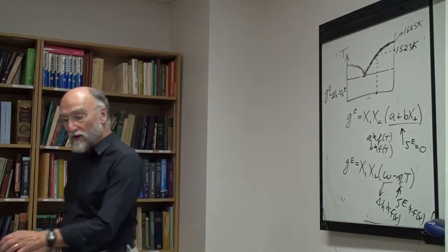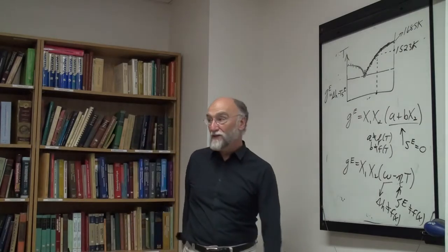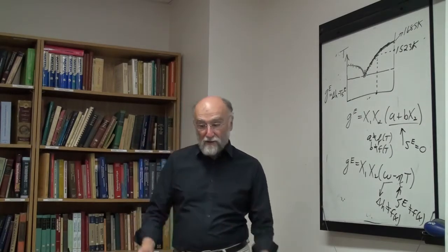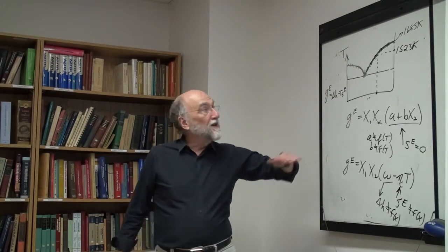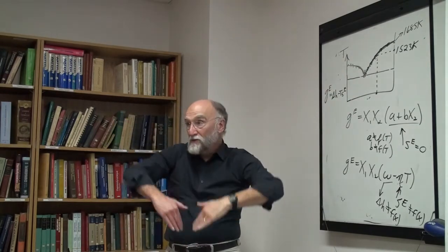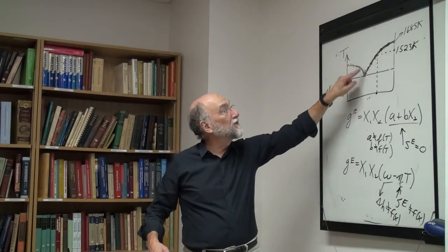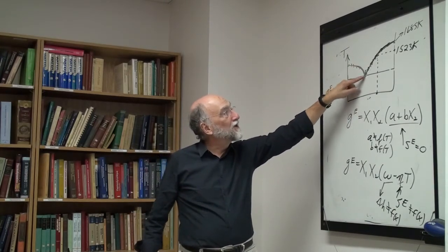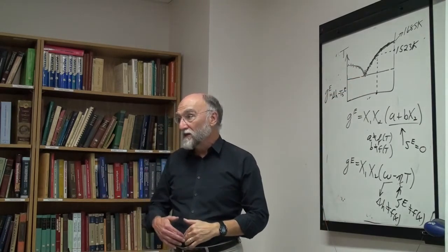And why is this important? If all you're trying to do is fit the binary phase diagram and reproduce the liquidus, it doesn't matter. But if you're now, say, trying to go from this system into a ternary system, then in the ternary system you may want to go down to other temperatures. Okay, in the ternary eutectic, and here the liquid phase only goes down to here. But in the ternary system, the liquid phase may go down another couple of hundred degrees to a ternary eutectic.